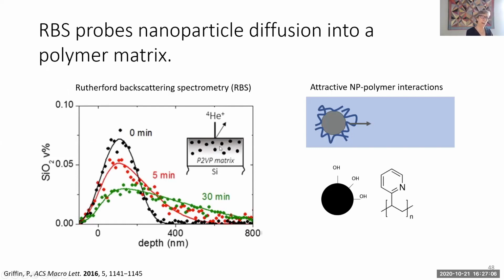So this experimental method is called Rutherford backscattering. It's helium in, helium out. And the energy of that outgoing helium tells you how deep inside the sample is the silicon. And so this is the silicon concentration profile. And just like we did before, we can get a diffusion coefficient from that concentration profile. The chemistry that we used in this set of experiments is P2VP, which has a very favorable interaction with bare silica. So that nitrogen likes to nestle in with that OH group, and we have an attractive interaction between the polymer and the particle, and we're going to watch how that particle moves.